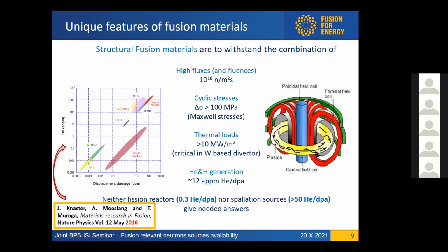Typically, a fission reactor is yielding 0.3 atoms of helium per dPa, which is substantially lower. And spallation sources, we have one in Belgium, the construction one. Spallation sources are okay. They are sold sometimes as a solution, but they cannot be, because again the spectrum is very wide, and in particular, in what concerns the swelling of the materials it is radically different, because the generation of helium atoms is above 50 per dPa.